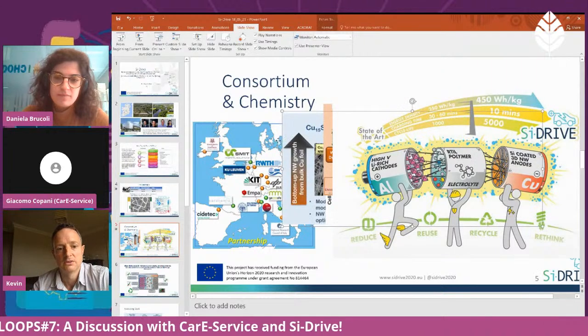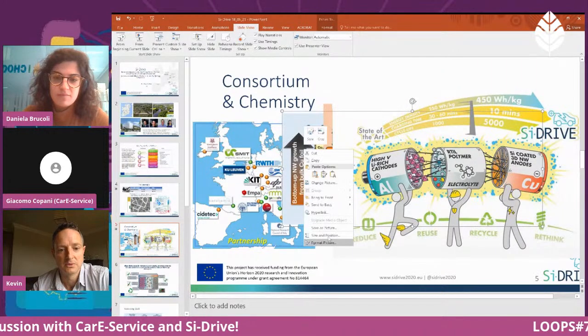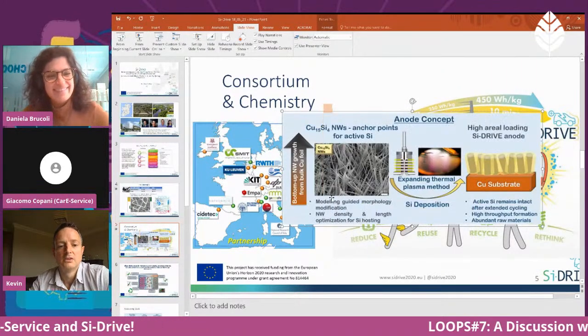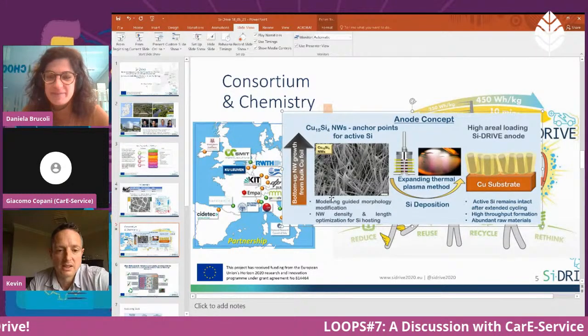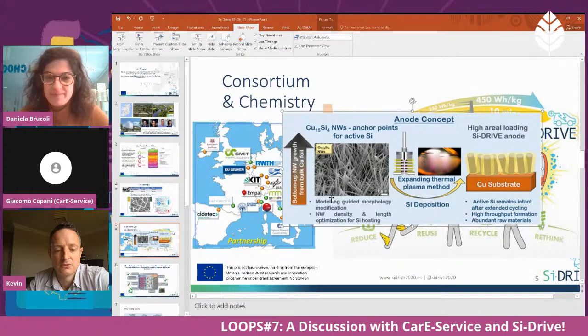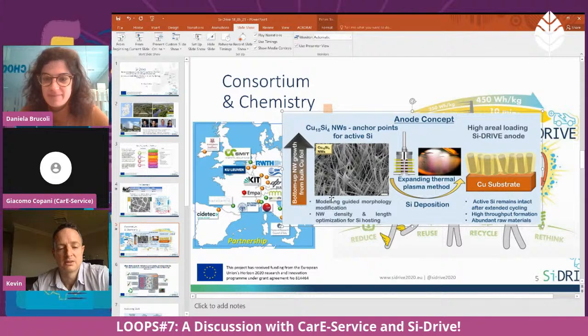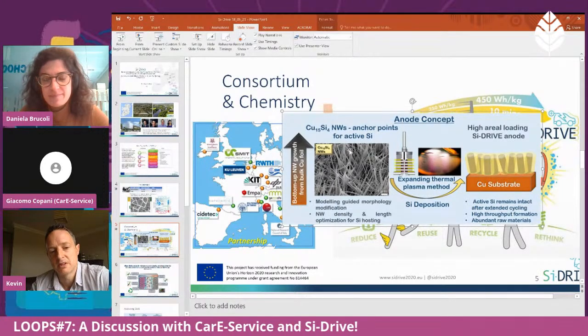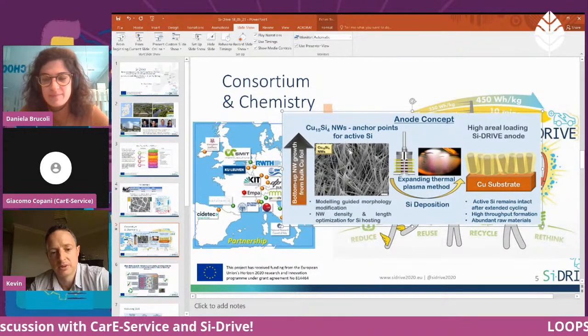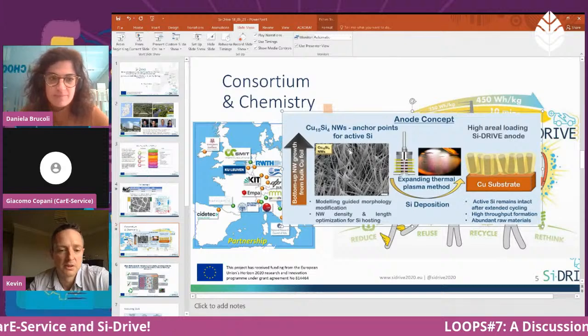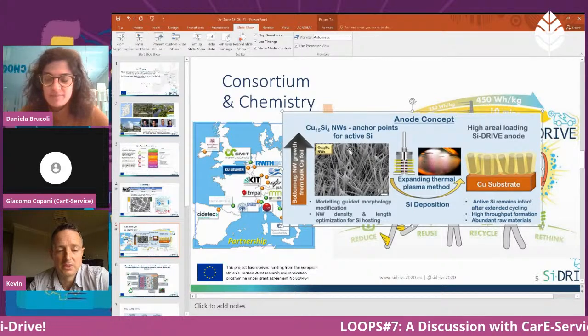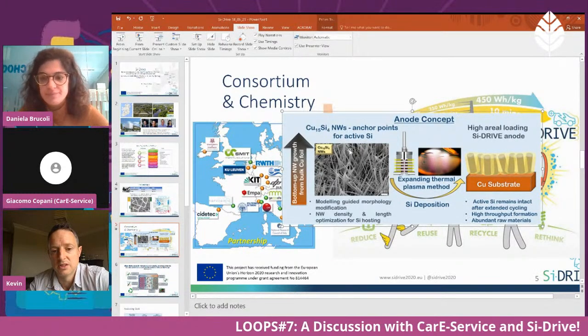looks like. So I'll just bring this to the front. I know this is a little bit awkward, but this is, I suppose, just to give context to the chemistry involved. So at UL, we have developed a process to grow copper silicide nanowires directly from a copper substrate. So the copper is essentially the electrode, and we can control the density and orientation of these nanowires.